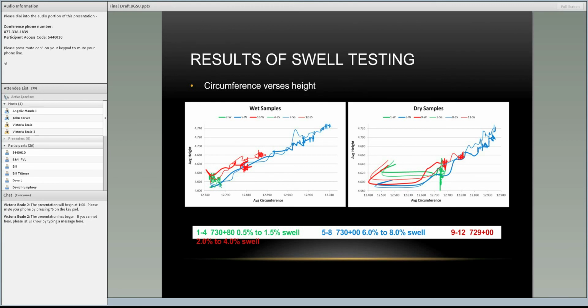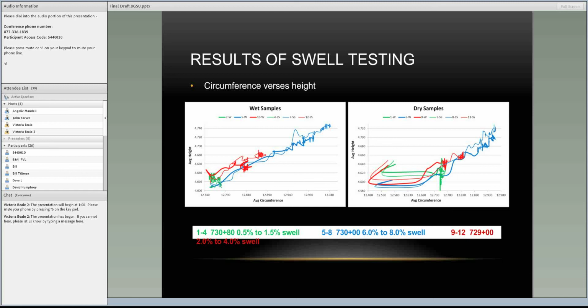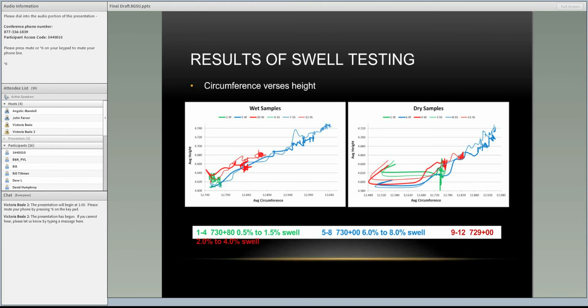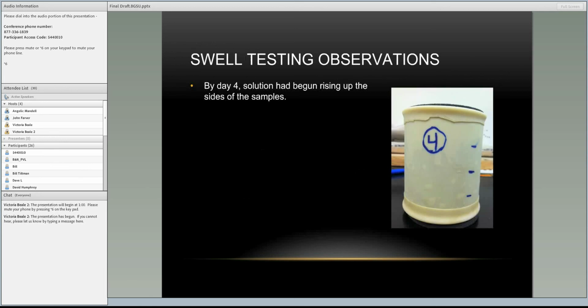Some observations that were noted during the swell test. By day 4, solution had begun to be visible rising up the sides of the sample. I don't know if you can see it here, but that's about the moisture line there. So this is a water sample, and the water has risen up through the sample and is about right there by day 4. And here is the sodium sulfate sample at day 4, and there's the line right about there.